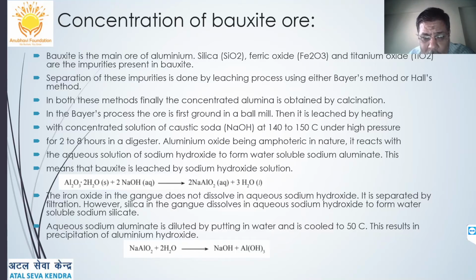First is Bayer's process. In Bayer's process, the ore is first ground in a ball mill, then it is leached by heating it with a concentrated solution of sodium hydroxide, that is caustic soda, at 140 to 150 degrees centigrade under pressure for 2 to 8 hours in a digester. It will form sodium aluminate and water. Aluminium oxide, being amphoteric in nature, reacts with sodium hydroxide or caustic soda to form water soluble sodium aluminate and water. So in this way bauxite is leached by sodium hydroxide solution.